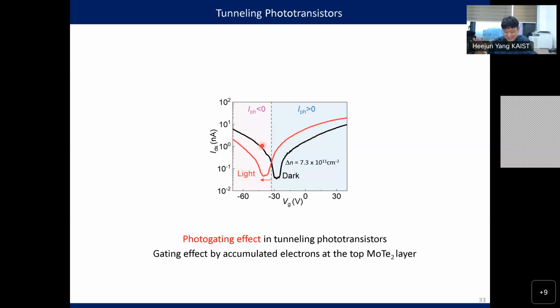So a hole exists in the conducting channel. And then this is called the transfer curve. And then we have a shift under the light illumination. The shift is coming from this doped or gated top MoTe2 layer.